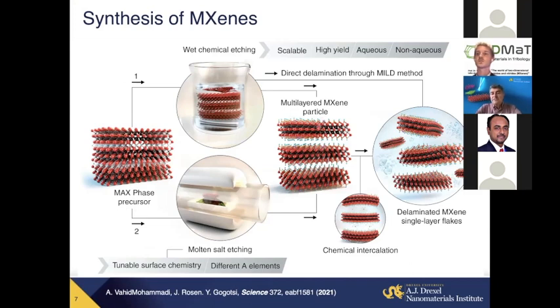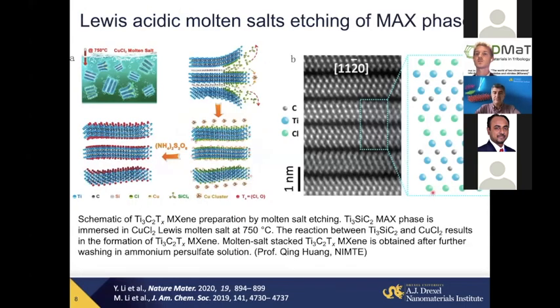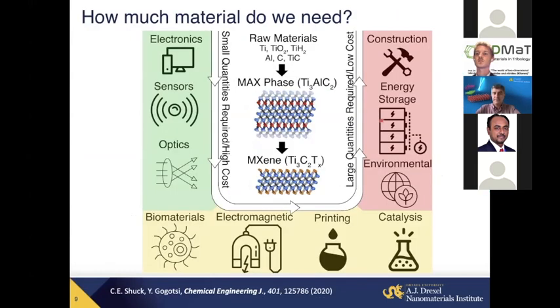We get particles which are bonded by weak van der Waals bonds, just like in, say, clay or graphite. And we can delaminate them into single layer flakes here. And this is an example of molten salt etched material when there are chlorine atoms on the surface now between the layers here. What is very important?